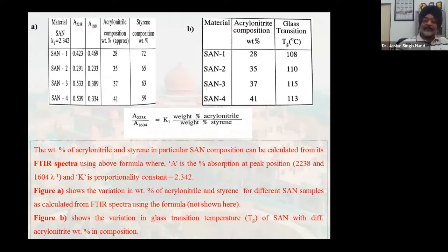different samples of SAN which contained 28% of acrylonitrile and 72% of styrene, and all this was verified using FTIR. So the heights of these two peaks were measured, and then ultimately we were able to calculate that SAN 1 has 28% acrylonitrile, 72% styrene. So composition varied from 28 to 41%.